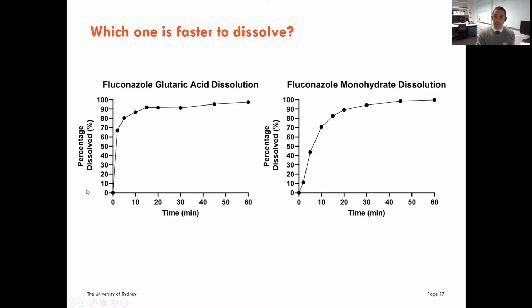Dissolution testing is essentially packing a certain quantity of the powder into a flow-through cell, and we run a certain liquid through there. We mimic the gastrointestinal fluid in this instance, so temperature, acidity, etc. And we take samples at different time points, and we measure how much fluconazole was in that sample at that time, okay? And as you can see, the results straight off the bat, at a time point of 2 minutes, we had almost 70% of our fluconazole dissolved into solution.